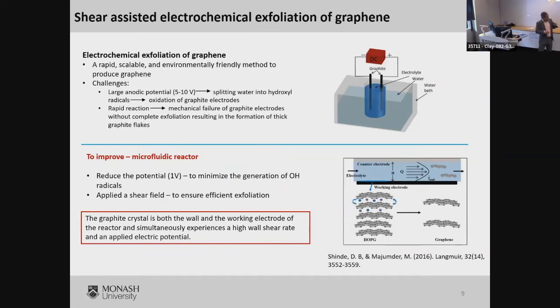Okay, so not the most ideal of methods, but if you characterize the product from those companies, you will find that it has mostly graphite flakes and particles. All right. So to overcome this, we started to think about whether we can use both shear forces as well as electrochemistry, and we found out that by using shear forces plus electrochemistry, we can actually produce graphene at quite a low potential, about 1 volt, compared to 5 to 10 volts.